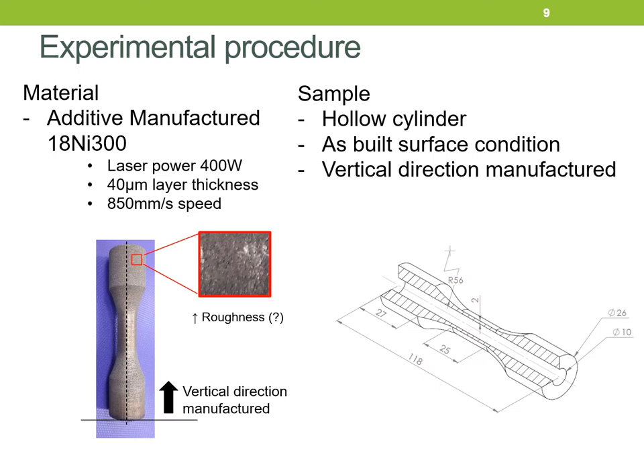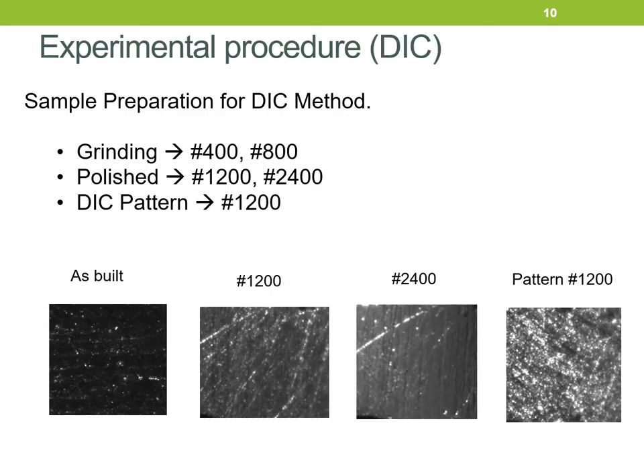The material is an additively manufactured maraging steel, 18-nickel-300. The manufacturing parameters are: laser power of 400 watts, 40 micrometers layer thickness, and speed of 850 mm per second. The sample was a hollow cylinder for the biaxial test, and the samples were manufactured in the vertical direction. A point to consider is the higher roughness present when manufactured in vertical direction, so the surface must be prepared before measurement.